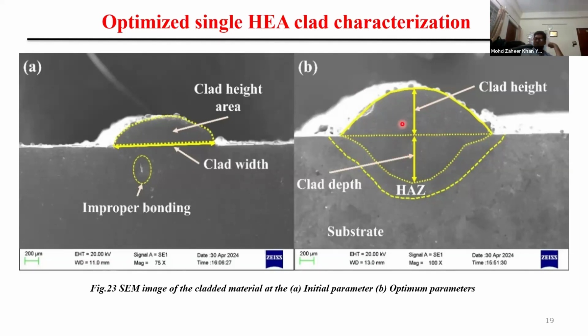And the material that is solidifying is actually a combination of substrate material and the clad material. So this clad material, which we wanted, let us say, of high entropy alloy, will now have a large amount of iron or mild steel also added to it. Similarly, if you are depositing a stainless steel powder, then this stainless steel will get mixed with iron, and the composition of the clad will be largely in between the composition of mild steel and stainless steel. And in this case, it may not offer the property desired from a clad layer. So it is important that mixing of the clad and the substrate should not take place.